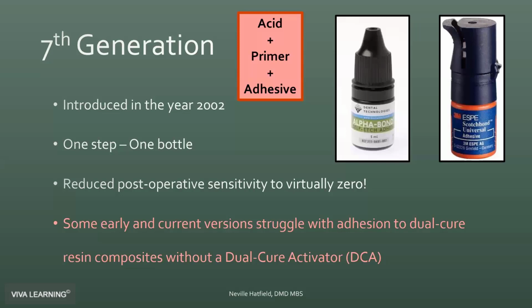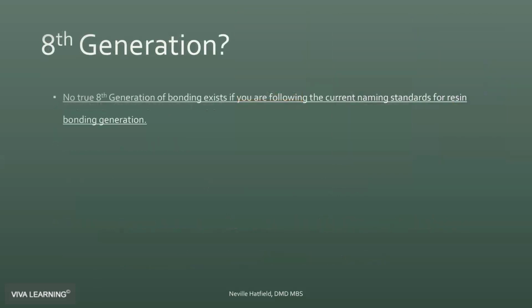So why the dual cure activator needs to exist is that the pH of these bonding agents is very low. It's below 3 pH. So what that does is that actually deactivates the initiator component, which is something called an aromatic tertiary amine, and it inhibits the polymerization reaction of the resin composites, which then obviously reduces the polymerization reaction and actually weakens the effective bonding to dual cure and self-cure resin composites. So the big question here, is there a true eighth generation?